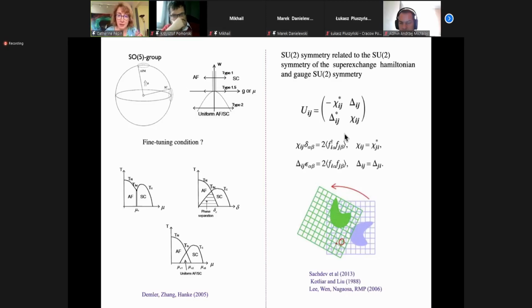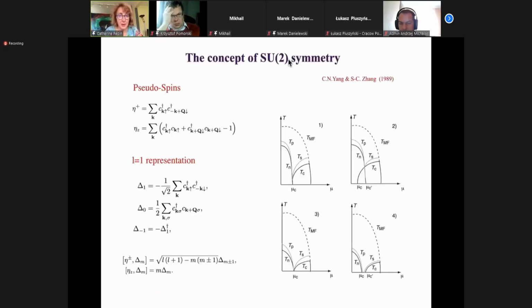So here, what we do, we don't fractionalize the electron. And we just have this simple rotation between charge density wave and superconductivity. Concept of SU2 symmetry. So this is for the half-filled case, this beautiful paper by Yang and Zhang in 89, also very soon after discovery of cuprates. So here is the helical representation with 2 superconducting order parameters because they have a phase, and 1 for the charge density with modulation, which is breaking translational symmetry. And we see that the rotation can be described by the pseudo-spin operator, which goes from one state to another. Here, L1 representation of a pseudo-spin.